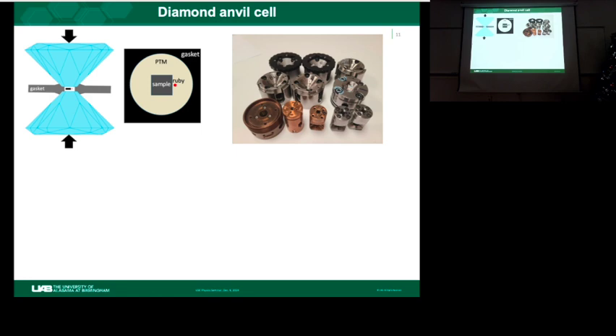And very often we want to have as much of a hydrostatic sample environment, so we put in a gas pressure medium or liquid, or sometimes even a solid like sodium chloride, a soft pressure medium, to have a quasi-hydrostatic environment. And this is a picture of a small part of the collection of diamond cells in my lab. It just depends on what type of experiment we do.